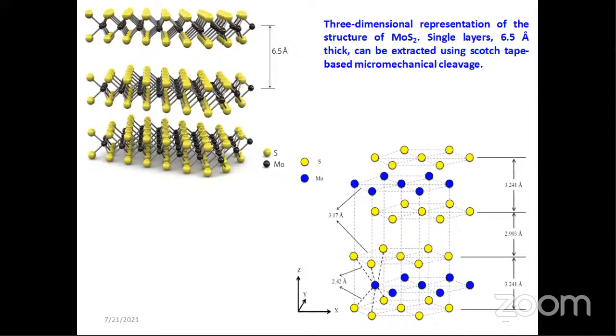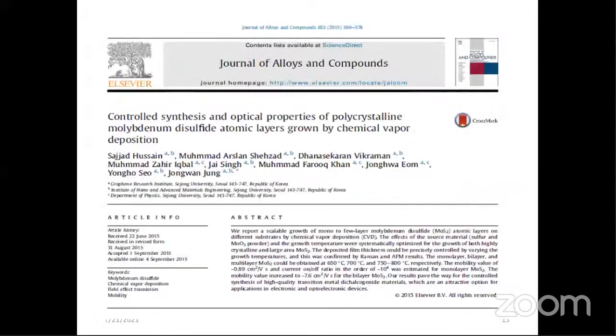Due to the weak van der Waals forces, we can usually remove this material with mechanical cleavage. So it can be easily synthesized by mechanical cleavage. But an important thing is that, as we know, mechanical exfoliation methods provide the purest MoS2, WS2, or graphene films, but the sample size is extremely limited by these exfoliation methods.